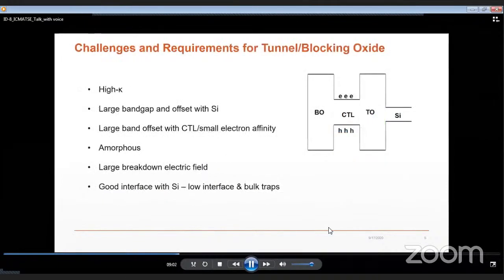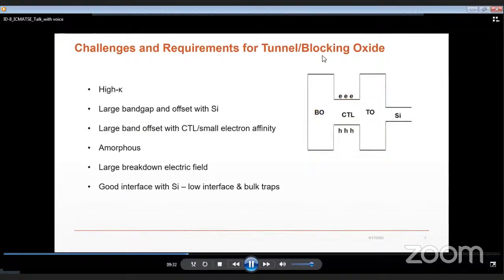For the memory to perform well, there are requirements for different layers in the device. This is a rough sketch of the energy band diagram of the flash memory. Here you see the tunnel oxide, blocking oxide, and charge trapping layer. The tunnel oxide material has to have a high dielectric constant, which allows the use of a physically thicker tunnel oxide with the same or even smaller equivalent oxide thickness of silicon dioxide. The main challenge remains in finding a high-K oxide with a good interface quality with silicon.